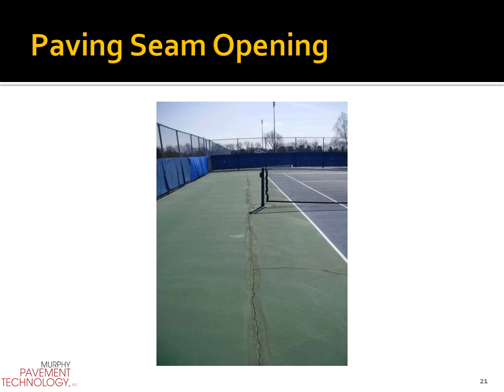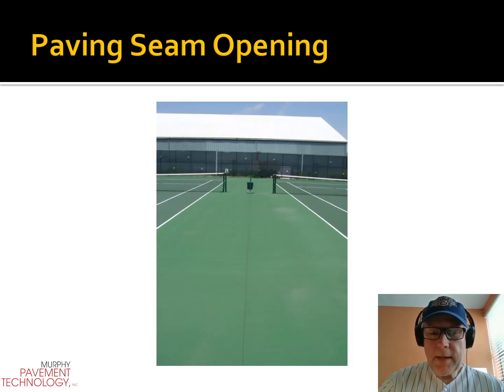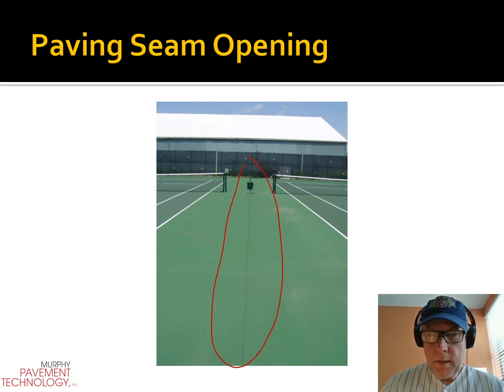And certainly we could move this seam further away from the tennis court, so a narrower laydown mat, but the owner should be prepared to route and seal that as part of the original construction process so that something like this doesn't occur. This is a very classic example of a paving seam that is opening up in a relatively short amount of time. These can be avoided. However, if you are going to build paving seams, you can control the crack by sawing and sealing them. It's certainly a much more viable option than doing nothing.